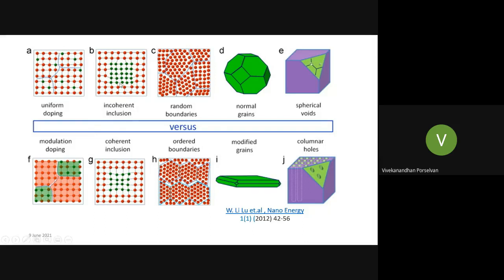Incoherent inclusion means that here we are including foreign atoms of nanoscale or ultrafine scale. Thereby, we are locally creating chemical inhomogeneity, and also we are making a certain kind of lattice misfit. We can see the ordered lattice, where the red-colored atoms are the parent atoms. If you look at it, we could not find any kind of misfit. Okay, so it is very uniform in all directions. If you look at the foreign atoms, given in green color, we can see that they cause some kind of lattice misfit, which means they are deforming the lattice structure.